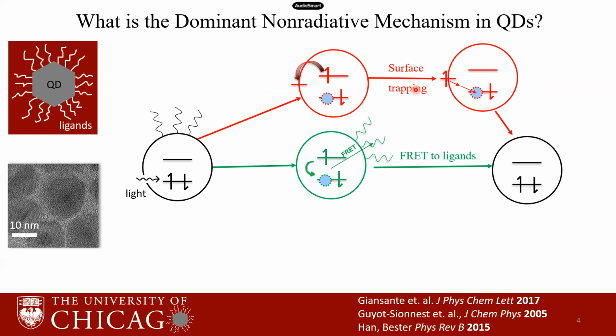The second non-radiative mechanism is unique to quantum dots in the mid-infrared. In this mechanism, the quantum dot energy relaxes non-radiatively and releases its energy to absorption of ligands on the surface. And this coupling is by a Förster resonance energy transfer. And this model is called the FRET model to ligands.